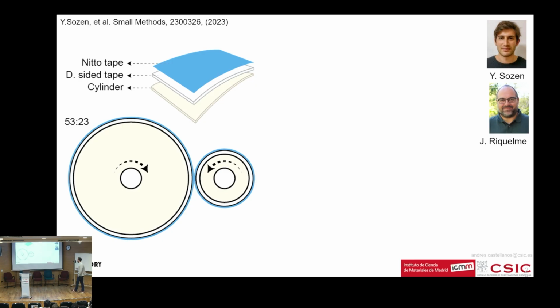The process is very simple. We have 2 cylinders. We coat the 2 cylinders with double-sided tape, and then on top of this double-sided tape, we put this Nitto tape, the one that you're passing through in the audience. Basically, we put these 2 cylinders coated with this Nitto tape to roll on each other. One important thing is that these 2 cylinders have perimeters or diameters that are 2 big prime numbers.